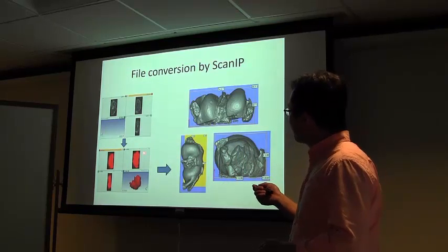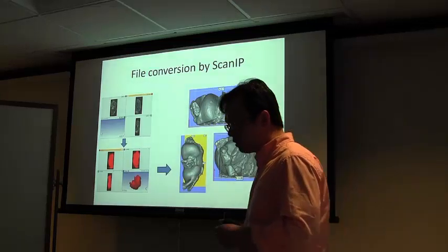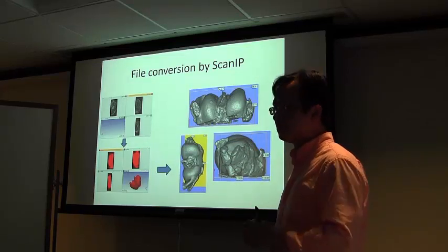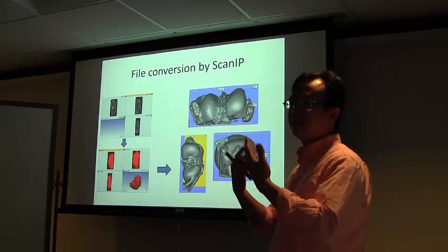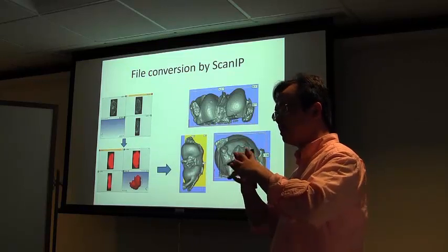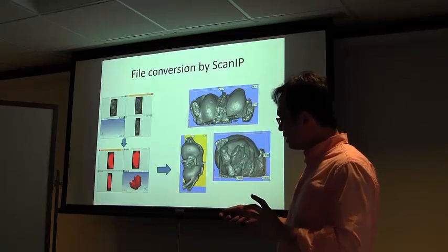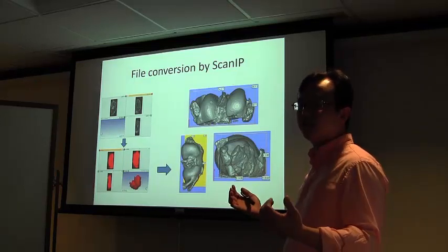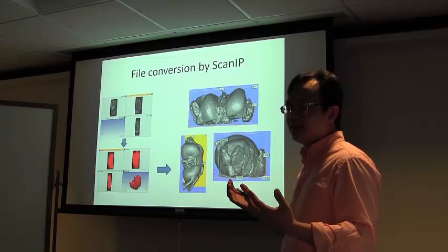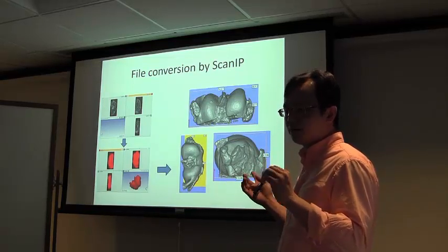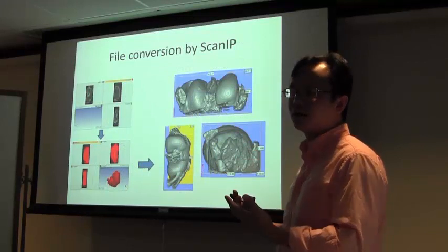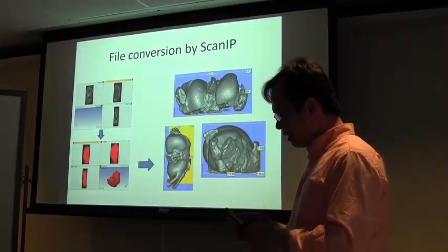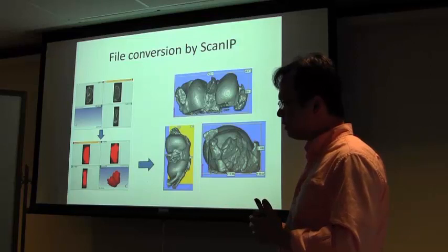Here, we're going to talk about some tricks. Let's use the bone as an example. Bone is a porous tissue, right? You get a lot of pores in the bone. When you do the micro CT scanning, you get all the details inside, from different pore sizes, different beam structures. So if you directly convert all the micro CT file of the bone to the 3D model, the file is huge, and it takes about 1 gigabyte. You get too much detail, and some of the details cannot be printed because they're too tiny or too soft. So the printer may use a lot of support to finally print something you want. So it's not very feasible.